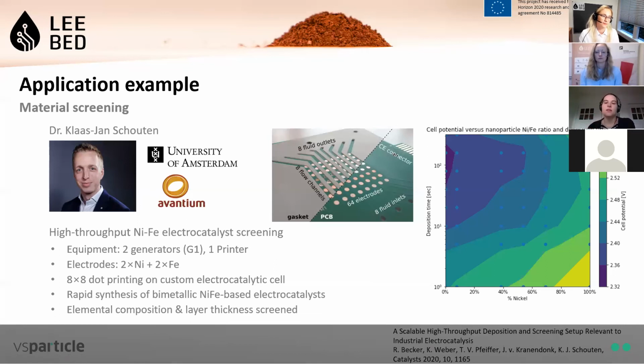So on the right hand side you see the cell potential of these 8x8 matrix. On the x-axis you see the nickel content compared to iron content, and on the y-axis you see the deposition time that varied from 1 second to 5 minutes. And yeah, so it was a really rapid synthesis method for these nickel iron based electro catalysts. It took in total 2 hours, and the results are really nice and are also already published.